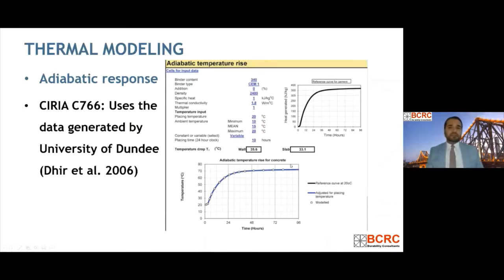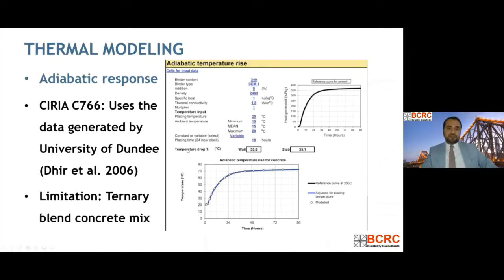But the issue is that it has certain limitations, right? This spreadsheet is based on the experiments which were performed in UK, and Australian cements are much different from the European cements, and the behavior can be different too. So you can estimate a wrong temperature. The other limitation that it has is that you can't use it for a triple blend concrete, right? You can see this option here, the binder type. You can only put one type, like either you can put fly ash in it or you can put slag.